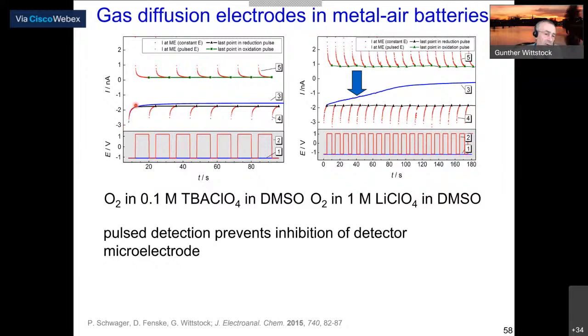The last point of these transients is taken, and if we connect that, we get the perfect line in the electrolyte, which was anyway good. But also in the lithium perchlorate, that recipe works. We take the last point, and then we get a stable recording for the oxygen permeation into that solution. The price we have to pay for that is, of course, a longer measurement time, because we always need the cleaning pulse and the measurement pulse instead of just measuring one value.